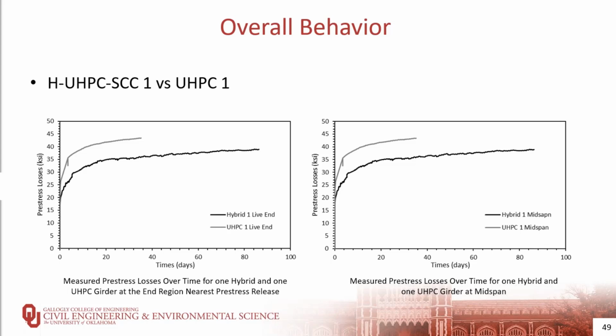However, the UHPC losses at midspan were higher over the first 20 days, and that's due to the higher compressive force transferred from the live end to midspan. This also could be due to the cracking that we actually observed on the top flange of the UHPC girders at multiple locations, reducing the moment of inertia.